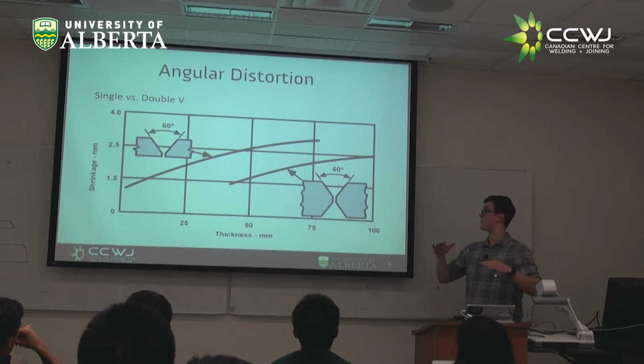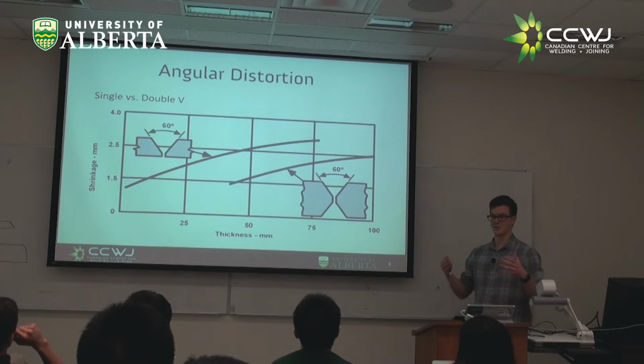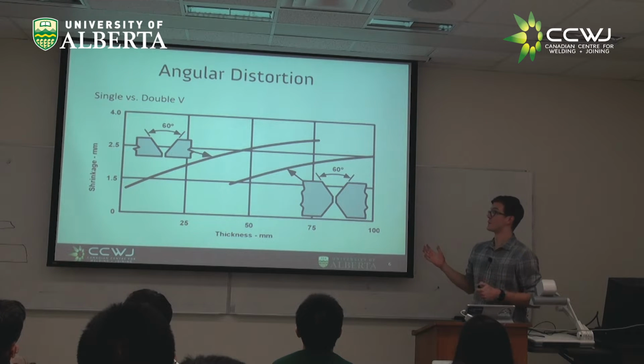You're kind of bringing it back into its original shape. Now that doesn't necessarily mean you're reducing those stresses, because you're still having restrained material. Whereas you put those additional passes in, the first passes are now actually going to be stressed back the other direction. But the overall distortion, angular distortion, should be reduced.